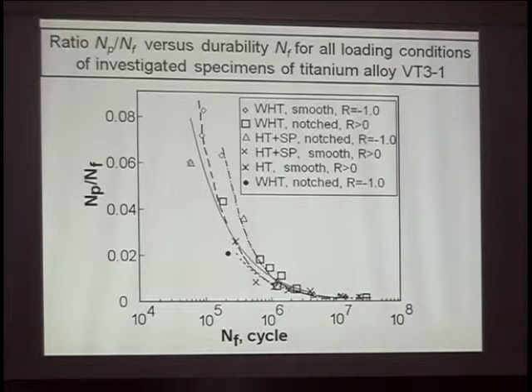Did the crack grow after each cycle, or did you have to apply several cycles and then it jumped? In my opinion, in terms of crack growth rate less than the distance between two atoms, it will only be jumping. It's impossible in conventional material cracking between these two atoms. That's why if we see lower crack growth rates, it will also stop and jump, stop and jump. Maybe the crack just has a very specific increment: one Burgers vector, 2, 3, 5, but nothing between.